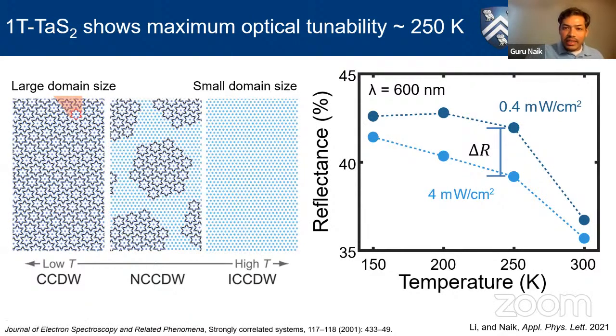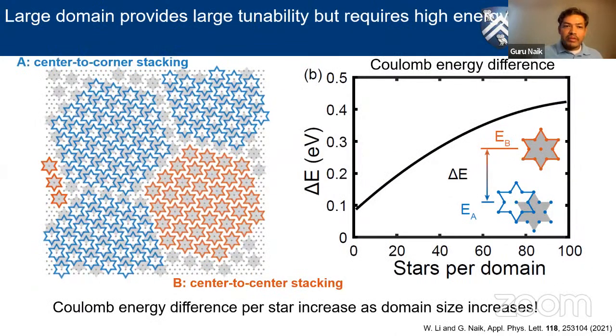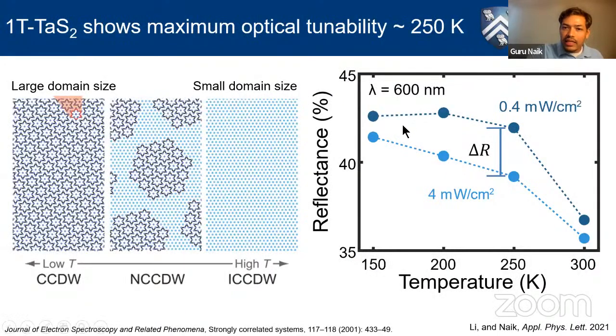So what we thought was, if we simply look at the Coulomb energy difference between the two stackings as a function of domain size, that is, number of stars per domain, this keeps growing. The energy difference between the two stackings simply grows with the domain size. So if the domain size in the limit goes to infinity, we should see a huge energy cost for switching from one stacking to another. Which means in the commensurate phase, at very low temperatures, we shouldn't be seeing any appreciable change in reflectance, because that's not energetically favorable. But we still see change in reflectance. So that's one thing that was surprising.